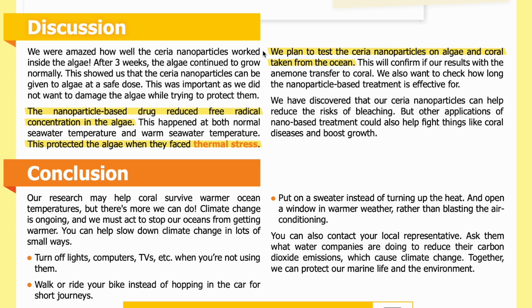Discussion. We were amazed how well the ceria nanoparticles worked inside the algae. After 3 weeks, the algae continued to grow normally. This showed us that the ceria nanoparticles can be given to algae at a safe dose. This was important as we did not want to damage the algae while trying to protect them. The nanoparticle-based drug reduced free radical concentration in the algae. This happened at both normal seawater temperature and warm seawater temperature. This protected the algae when they faced thermal stress.